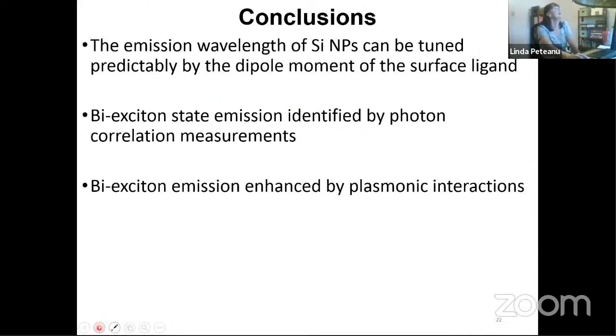So to conclude, basically the emission wavelength of the silicon nanoparticles can be tuned in a predictable way by changing the ground state dipole moment of the surface ligand. Biexciton state emission can be clearly identified by photon correlation measurements and can be enhanced by plasmonic interactions, which can also be used to identify it.